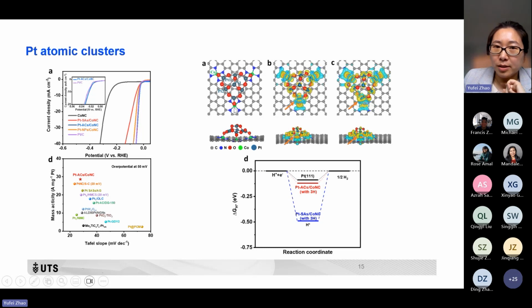One is from the interface, which is cobalt, oxygen, platinum here. And another one should be the platinum, oxygen, platinum on top of these clusters. When we do the charge redistribution, we found that at the interface, very heavy charge has been transferred from the metal to oxygen. But on top, in the platinum, oxygen, platinum part, much less electron has been transferred. That means the platinum in the platinum-oxygen-platinum unit has much higher electron density compared to the interface. So this site may contribute more to the HER catalytic activity.